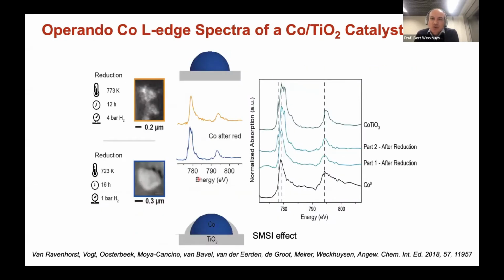So back to this cobalt titania catalyst. You have references, cobalt titania and cobalt metal, and you can reduce the catalyst in different ways. You can, for example, see that when you reduce it in a certain way, you measure almost a spectrum which is cobalt titania.